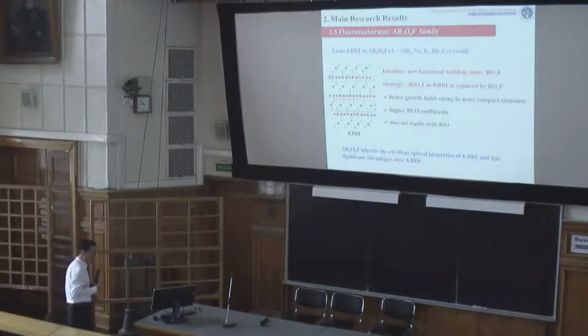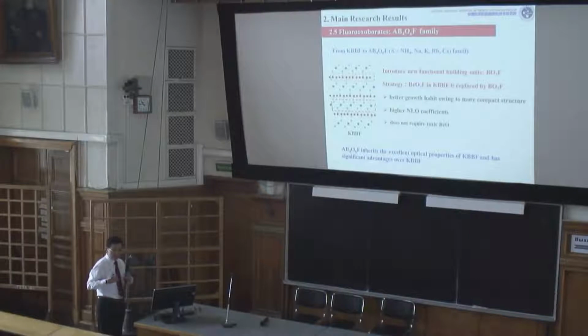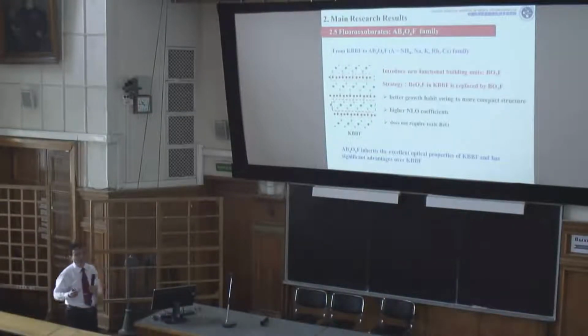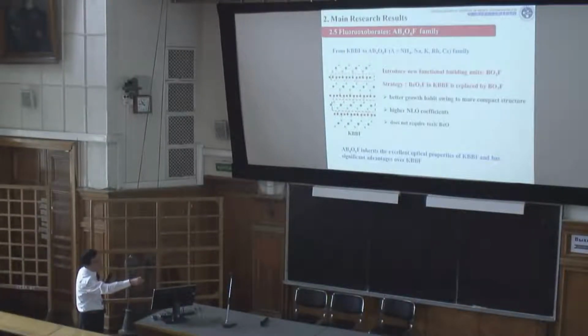And also, we still want to search for suitable compounds that produce deep UV laser wavelengths. We want to base on KBBF, and search for new materials. In fact, we want to substitute BeO4F in KBBF by BO3F, because a moment ago I mentioned this unit may be the best candidate for producing a large band gap, large SHG response, suitable birefringence, and we also want a material with better growth habits and higher NLO coefficients. This material doesn't require toxic beryllium. Okay, we found the AB4O6F family. This family inherits the excellent optical properties of KBBF and has significant advantages over KBBF.